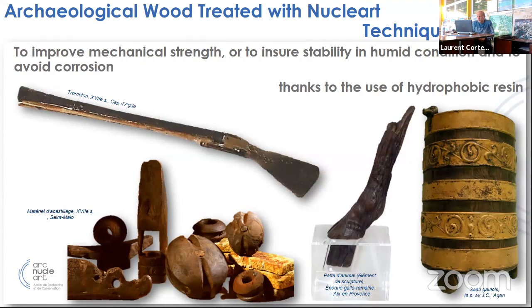Something very important, it avoids the corrosion when metal is associated with wood. That is the main problem of PEG treatment, because conventional PEG treatment with freeze drying is very hydrophilic and will cause corrosion of metal when it is associated with wood.